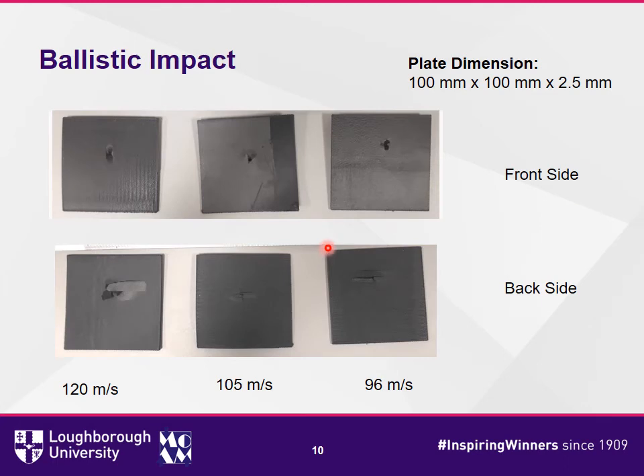Having the properties of the material, a few initial ballistic impact tests were carried out, ranging from 96 meters per second to 120 meters per second. A gas gun was used for the experiment with steel spherical bullets of 9 millimeter diameter. Calculating the energy for such velocity ranged from approximately 14 joule to around 20 joules. After the impact test, looking at the backside of the plate shows significant delamination, which is the main failure criterion of this material. This indicates poor bonding strength between the layers in the material, which could be due to the porosity created between the filaments during the extrusion process.